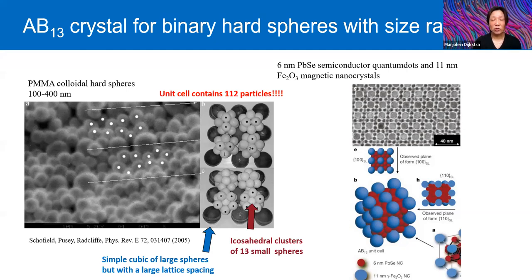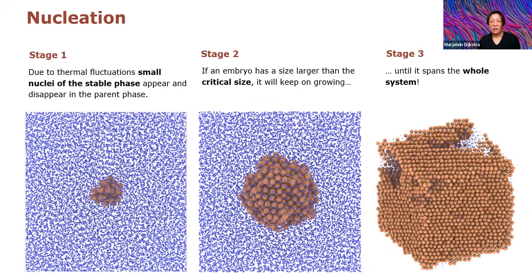And the total unit cell consists of 8 of these icosahedral clusters, and at the corner there are all these big spheres. So they contain 112 particles in the unit cell. And they are observed for big spheres, but also in the nanoparticle regime. So if you really want to understand how such a crystal can form from just mixing big spheres and small spheres together, we have to go back to nucleation. Nucleation is that due to thermal fluctuation, small nuclei of the stable phase already appear and disappear in the disordered fluid phase in this case, until the crystal nucleus exceeds the critical nucleus size, and then this cluster will grow out until it spans the whole system.